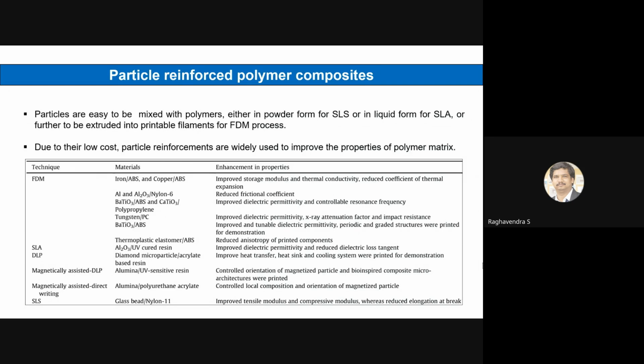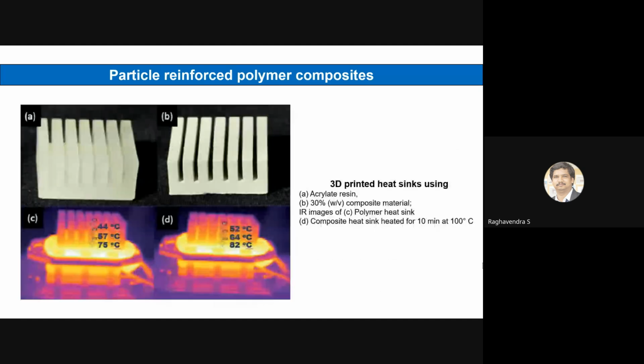Similarly in SLA also, as I told you earlier, you can add particles directly to the resin itself, like aluminum oxide slash UV cured resin. Here also there is improvement in dielectric permittivity, and similarly for DLP. I will show some case examples after this, where you will be able to understand this. A magnetically assisted DLP process itself has been developed. We'll look at it in the coming slides, how you can control the alignment of the particles you are reinforcing, so that you will get a highly isotropic part. That is the focus which we want to get.